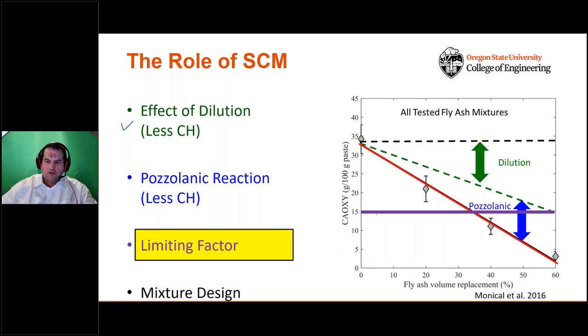The second thing you can do is you can say, how do I utilize other materials other than cement inside of my concrete to make good concrete? So this graph that we see over here is fly ash, although we have very similar graphs for lots of other flavors of SCM. If we have a plain OPC system, we're right here at the 0 point. As we add fly ash to the system, what we notice is the amount of oxychloride decreases, and it decreases primarily due to dilution. We simply have less cement, we have less calcium hydroxide.